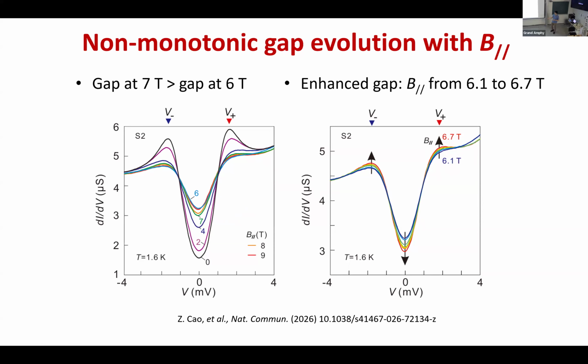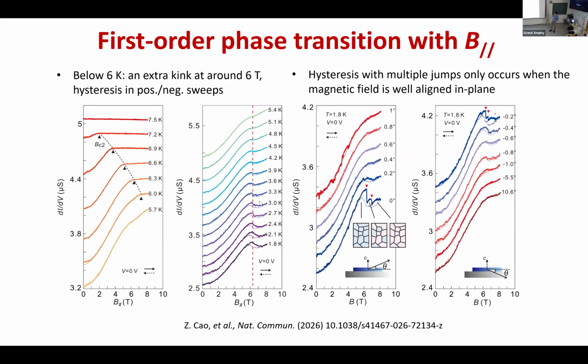Now if we stay at zero bias and just plot the tunneling conductance as a function of the in-plane field, then we see the first order transition. At low temperature, we do see some hysteresis. And this field is the field where the upper critical field shows an upturn. So it's consistent with the expected first order transition.